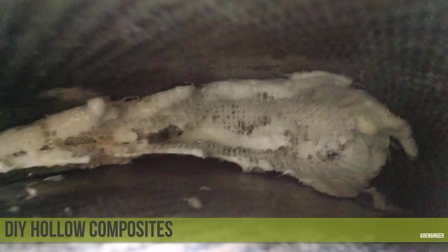And it goes back to the Champion Motorsports example, where they show themselves sealing that part, either with some mold release or a gel coat or even some Vaseline, sealing it so that you don't get a strong bond. Because it will melt away, it will dissolve away, but the ends, the kind of outer skin, will come away in chunks, and it's really just epoxy. So there's lesson number 3 there.